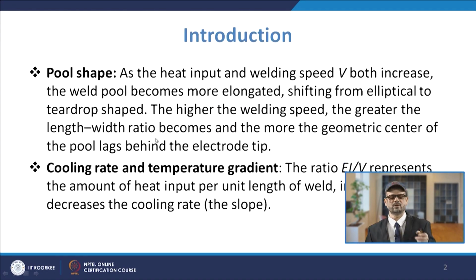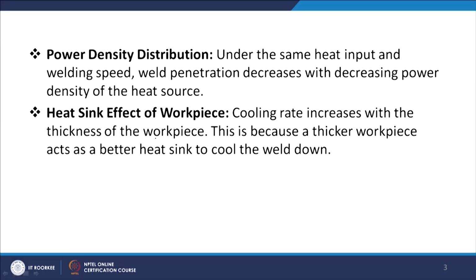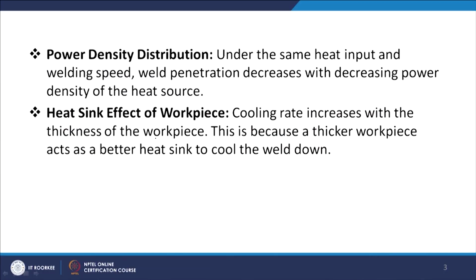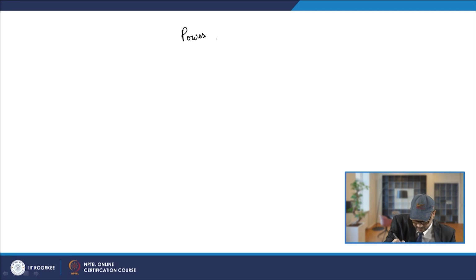The next parameter which is important is the power density distribution. So, you have the power density distribution of heat source as an important parameter, and so under the same heat input and welding speed, the weld penetration will decrease with decreasing power density of the heat source. So, you have different types of heat sources, and you have different power densities. So, that can be understood by the figures. So, we will have the effect of the power density distribution.